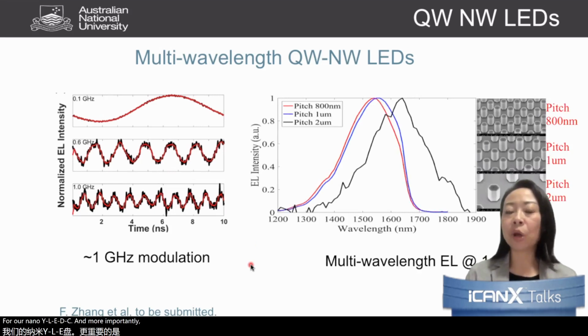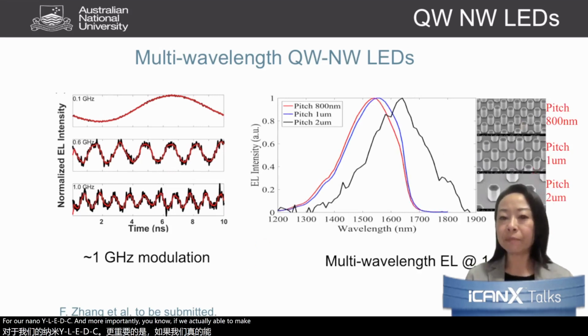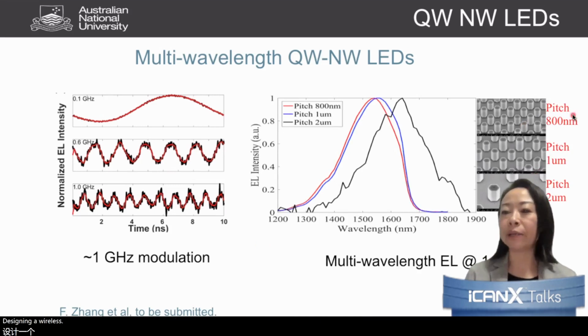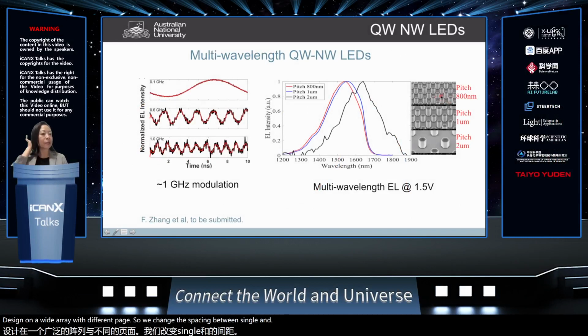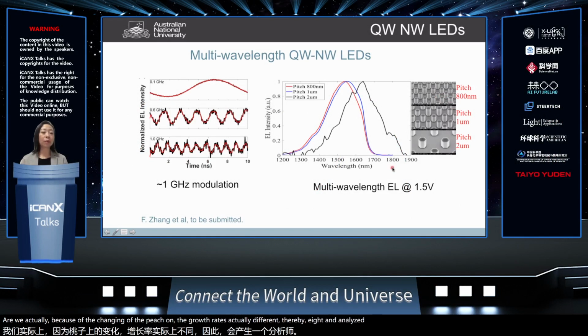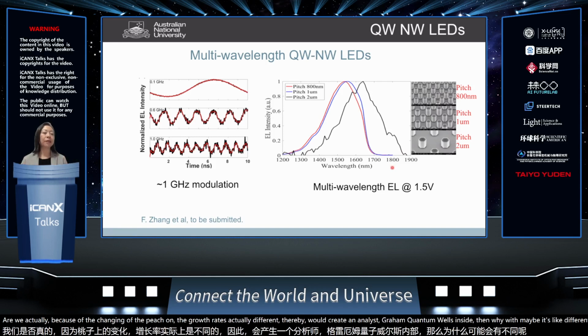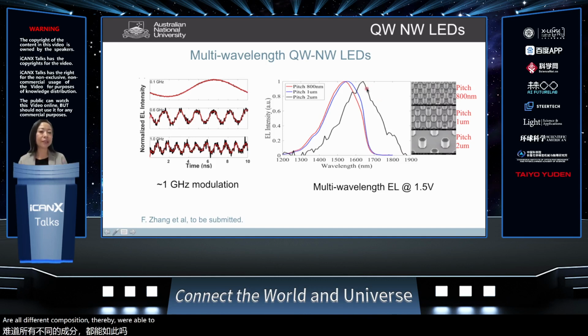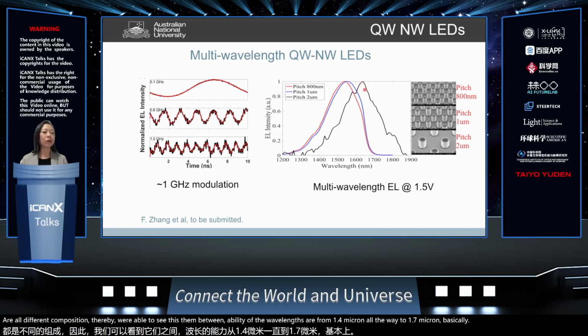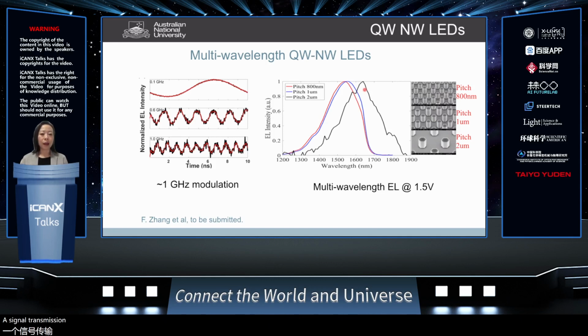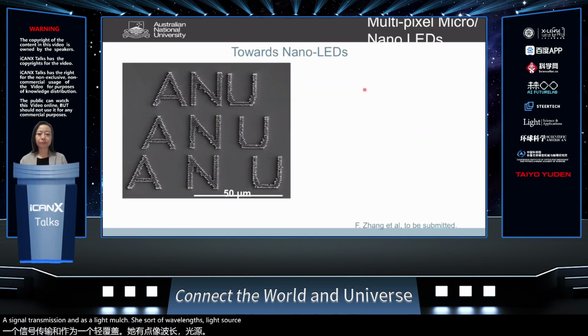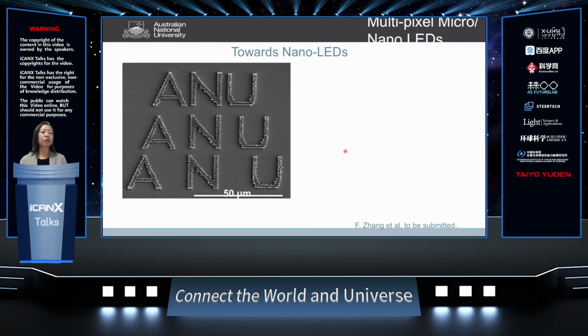And more importantly, from the same fabrication growth, we can design nanowire arrays with different pitch. So we change the spacing between single nanowires. Because of the change in pitch, the growth rate is actually different. Thereby we create quantum wells inside nanowires with different thickness or different composition. Thereby we're able to see this big tunability of the wavelengths from 1.4 micron all the way to 1.7 micron, basically showing that you can create multi-wavelength LEDs, which is very important for signal transmission and as a multi-wavelength light source. And certainly, there's a lot of interest in nanoscale LEDs because of the size as well as other important properties.